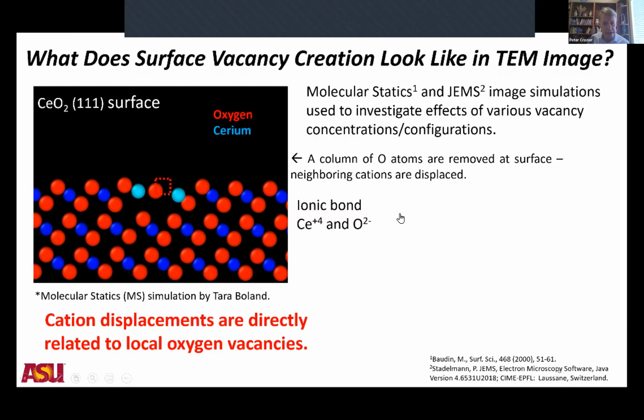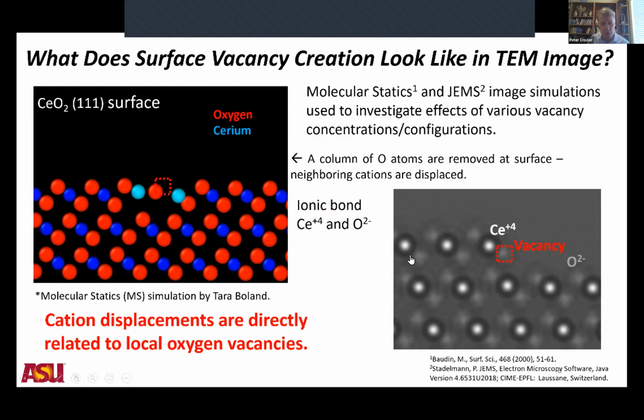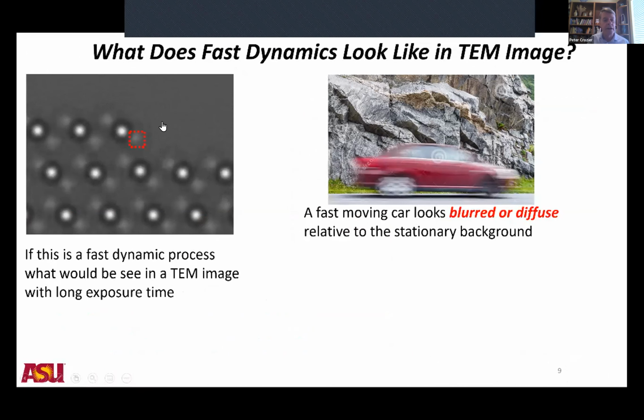And so she did that for a step and then used the molecular statics models to simulate the TEM images. And this is what the simulated movie of creating and annihilating an oxygen vacancy looks like in the microscope. And in fact, we realized that if you think about this, of course, this is going on very quickly. This is probably hundreds of femtoseconds is the time resolution for the molecular dynamics simulations.